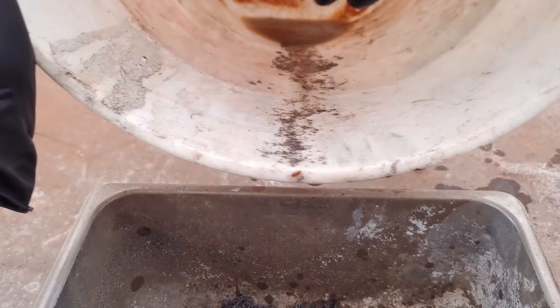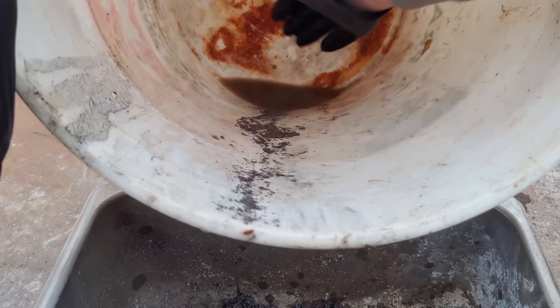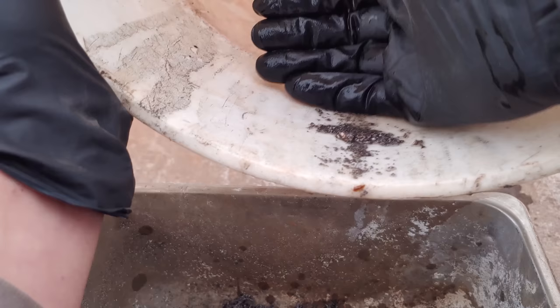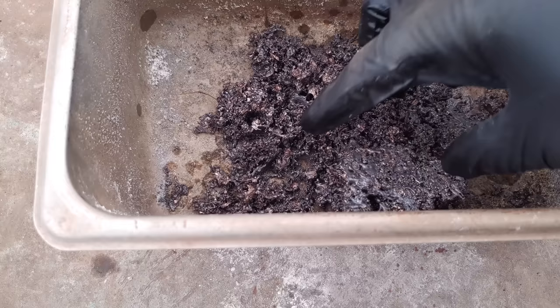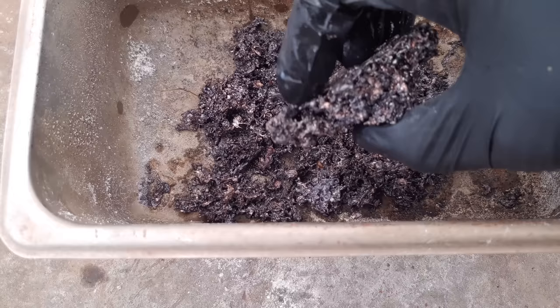Now what we're gonna do, because we have a huge amount of surface area on the lead, I can add a bunch of oxidizer and oxidize the lead and the copper and the base metals, all the junk in there we don't want, and all the precious metals will collect at the bottom. And then we'll have a much smaller button to work with. We don't have to cupel 500 grams. We might have to cupel 50 or maybe 20. We'll see what we come up with.